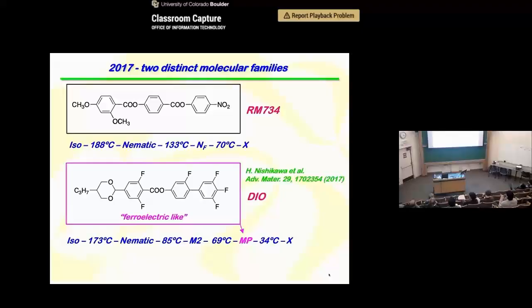Okay, so at the same time, actually the same year as RM734 was made, a Japanese group reported DIO. DIO is isotropic, a real nematic, an unidentified phase, and then this phase that they called ferroelectric-like. This attracted our attention, and Dave made DIO, and we looked at DIO. The main question is, is this ferroelectric-like phase the same phase as we have in RM734?